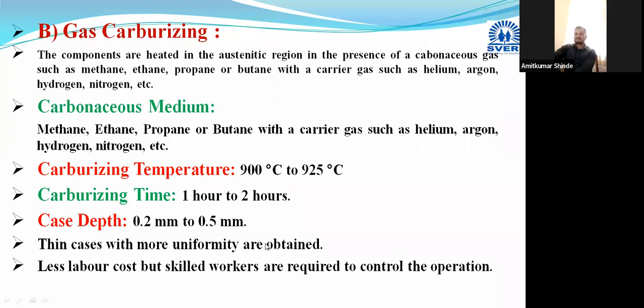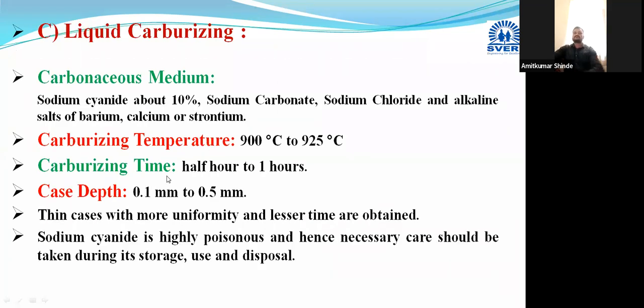Labor cost is also less if you compare it with solid carburizing. You can do the comparison related to the medium: carburizing temperature and carburizing time are less, thin case depths can be obtained, and more uniform cases can be obtained in gas carburizing. So after this we will move towards the third type, that is liquid carburizing.